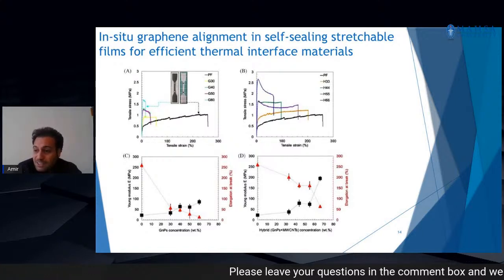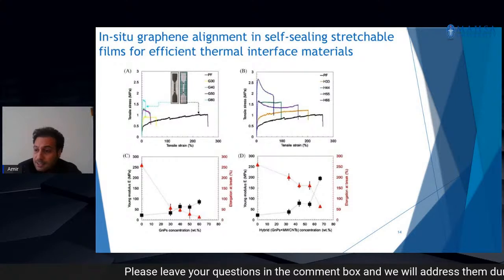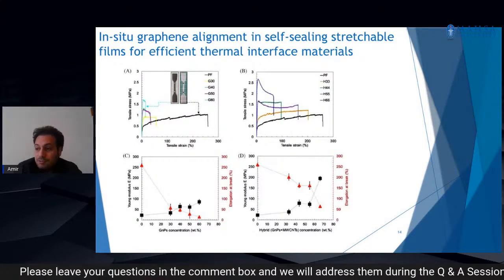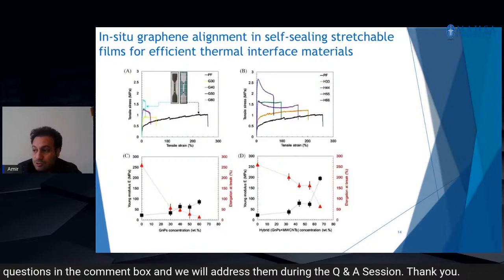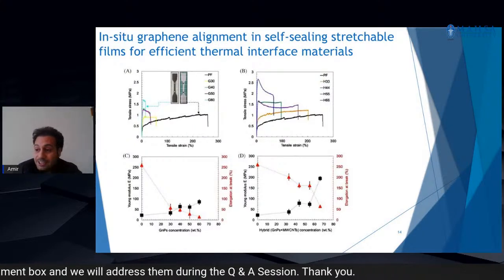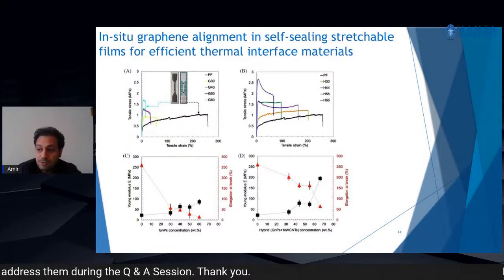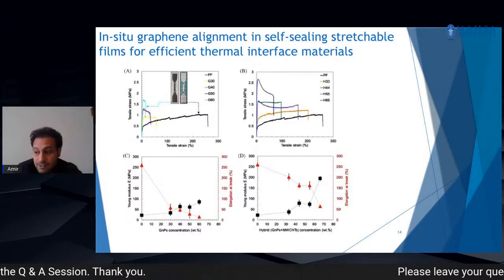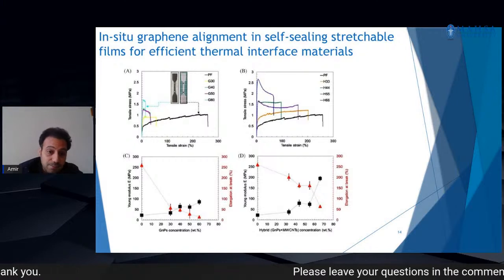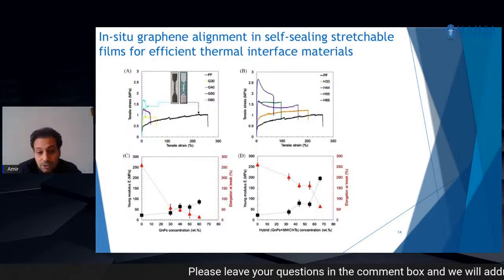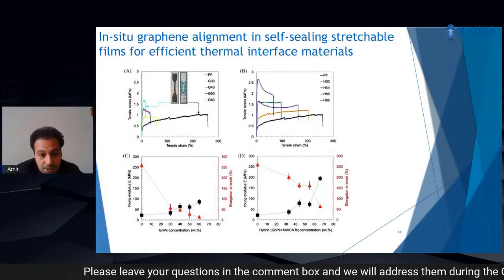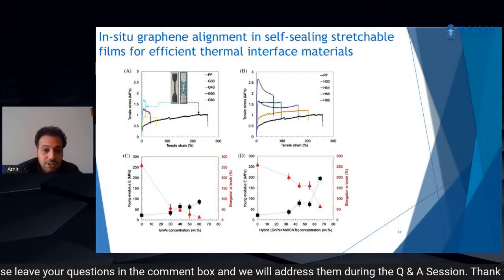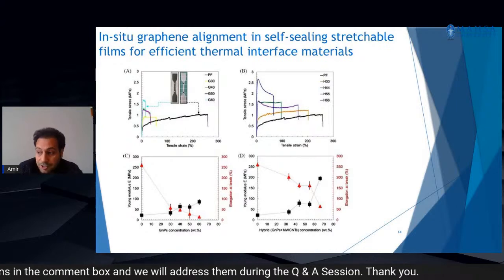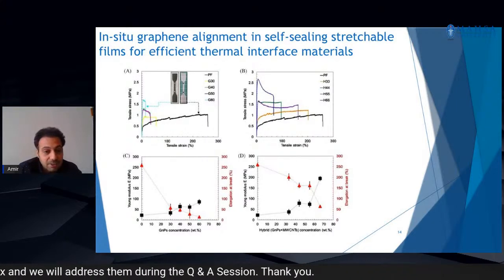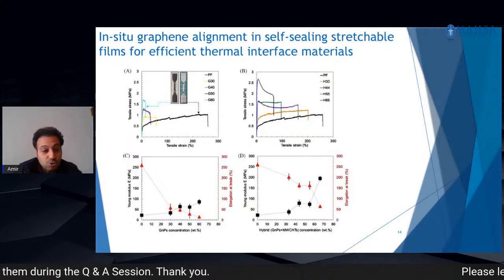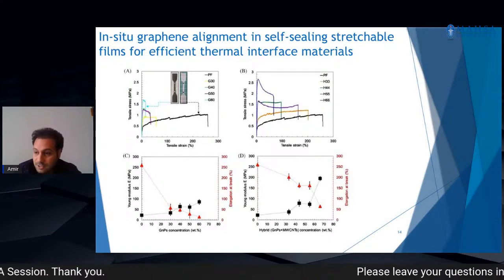Plot A represents the specimen fabricated for the tensile test, and Young's modulus E and elongation at break percentage values obtained from the nanocomposite samples with GnPs are in plot C. So we are comparing these two categories of samples and checking the elongation at break percentage value of each, which shows a clear big difference between these samples.